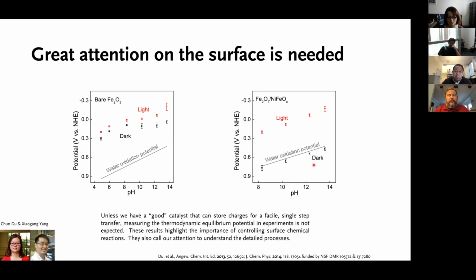So I said previously, on the previous slide, we're getting to the tricky part of this problem. This is because for most heterogeneous catalysts, like a solid electrode, the water oxidation mechanisms are not well understood. And hence, their electrochemical potential is all over the place, although the theoretical calculation shows it should be 1.23 volts under standard conditions. So this is getting very tricky, particularly if you're working with semiconductors, where the degree of band bending and hence the overall efficiency will be determined by the difference between the Fermi level of your semiconductor and the electrochemical potential. So we got frustrated.